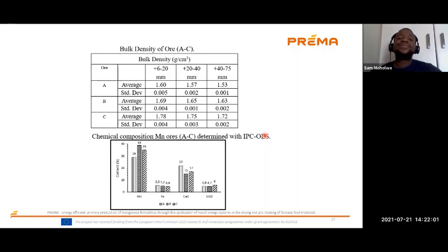Here we have the bulk density result. As mentioned, this bulk density was measured per size range. We have ore A, for which we did the bulk density for +6, -20 millimeter particles. We have it at 1.6 gram per cubic centimeter. Then as you increase the size range, you can see that the bulk density decreases, which is expected because as you increase the size range, your particles become bigger and more bulky, and if you put them in a certain volume, as we did in this test to determine the bulk density, we'll have the particles having more spaces between them.